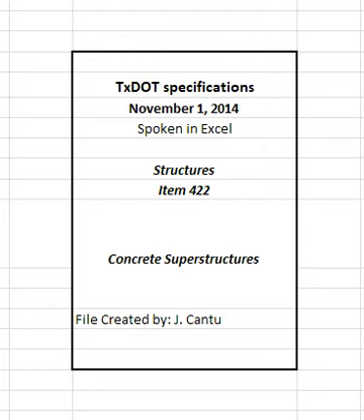Leave in place weight supporting forms and false work spanning more than 1 foot except as directed otherwise until the concrete has attained a compressive strength of 2,500 psi. Remove forms for other structural components as necessary. Forms or parts of forms may be removed only if constructed to permit removal without disturbing forms or false work required to be left in place for a longer period on other portions of the structure.